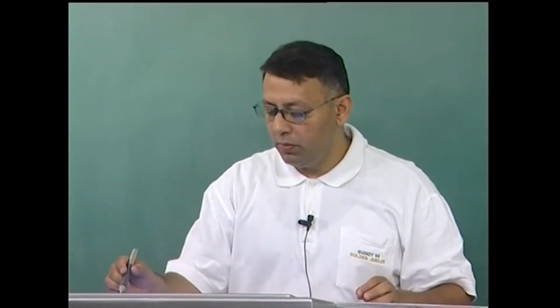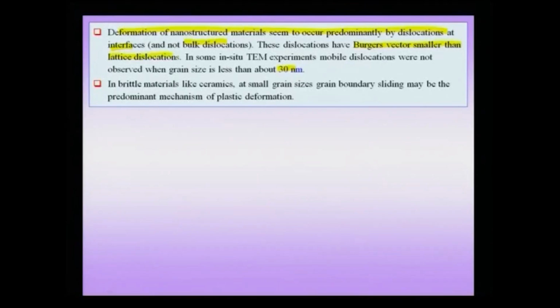And if these dislocations sit exactly at the grain boundary, then they seem to have a Burgers vector smaller than the lattice dislocations. In some in situ TEM experiments, mobile dislocations were not observed when the grain size is below 30 nanometer. That means TEM experiments have confirmed that when you go into really small grain sizes like 20 and 30 nanometer, there seems to be a paucity of lattice dislocations, and it is the grain boundary region which becomes important, including from the sliding perspective and also from the perspective of dislocation activity.